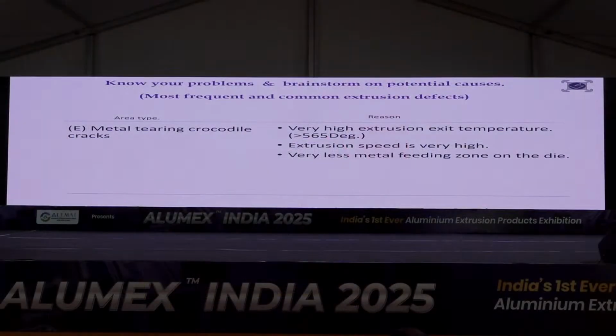For that, many people use exit temperature indicators with infrared sensors made by some Israeli and USA companies, which give instant temperature control, and your operator will control the speed. But if that is not controlled, you have to leave it to the operator's mercy. You will first see a couple of feet or a couple of meters damaged, then he will reduce the speed. In turn, the entire length is damaged because half of the part is damaged already. After that, even if you regularize the speed, it is still gone. So we have to be very, very careful here, and really follow the theory of isothermal extrusion.